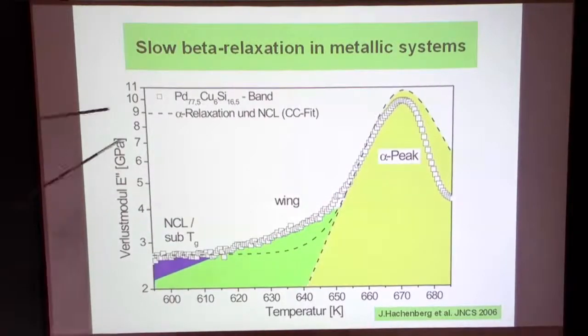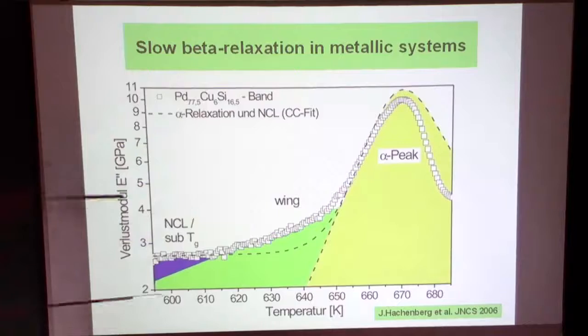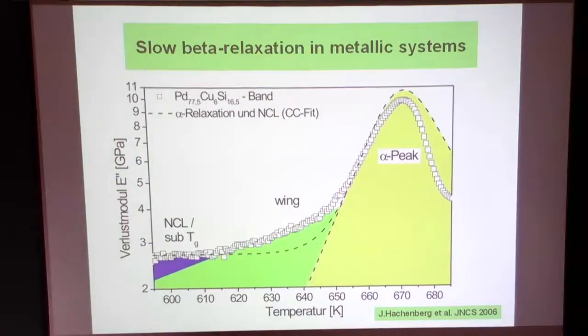And palladium copper silicon belongs to those, and those which are more strong ones, which are the zirconium, titanium, lanthanum-based ones, which have different, more oriented bond-like orientations in the d bonds and d electrons, and that's one which has different strengths, in what we call strong glass-forming systems.